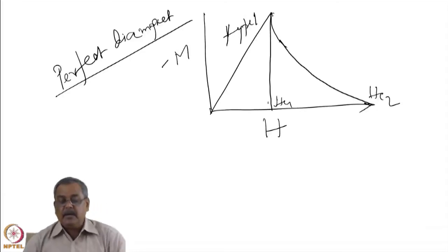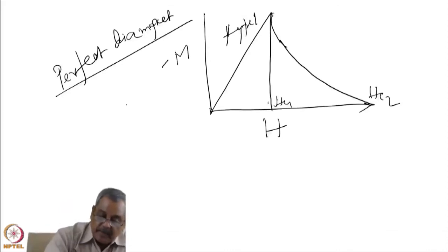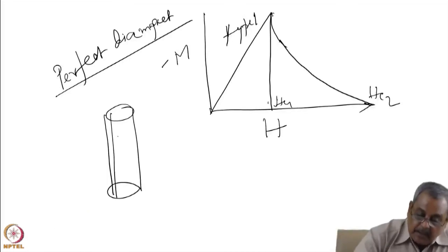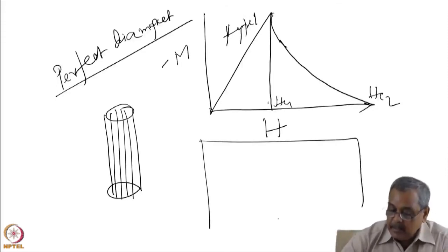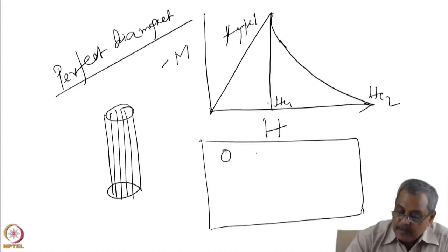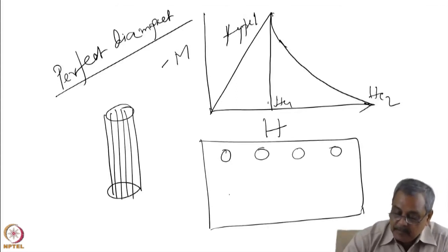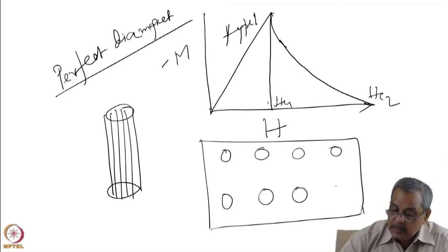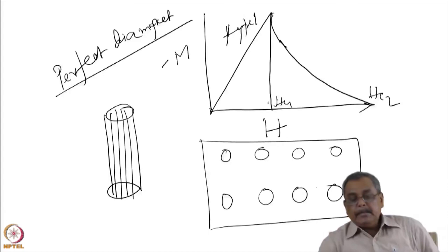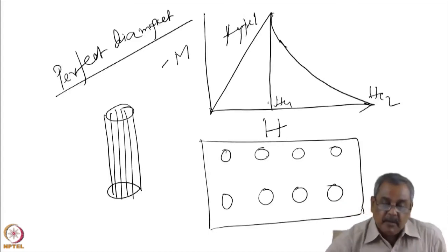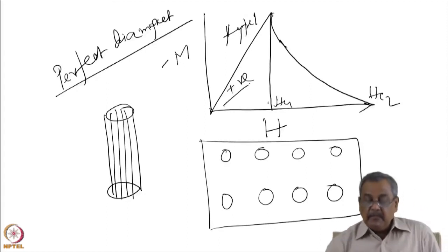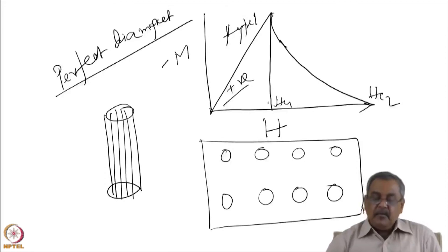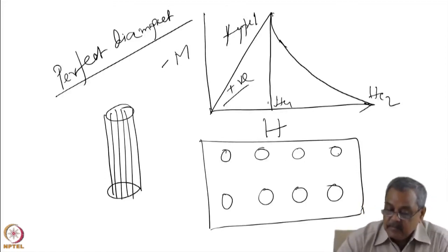In a type 2 superconductor, there are vortices, that means magnetic flux lines are in the form of vortices. If I take a superconductor cross section, there are these vortices which can come. This is because it was shown by Abrikosov and Gorkov that the surface energy of these vortices in type 1 is positive, so they don't form. But in type 2, the surface energy is negative. So the negative surface energy helps to reduce free energy, and you have this kind of vortices.